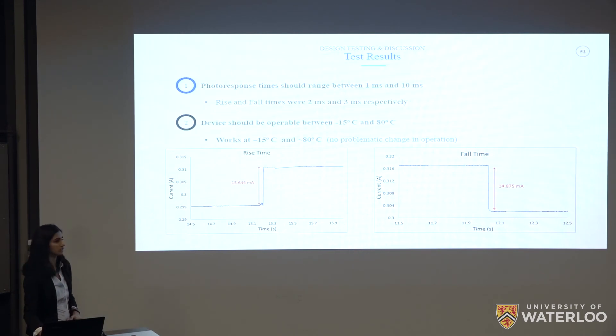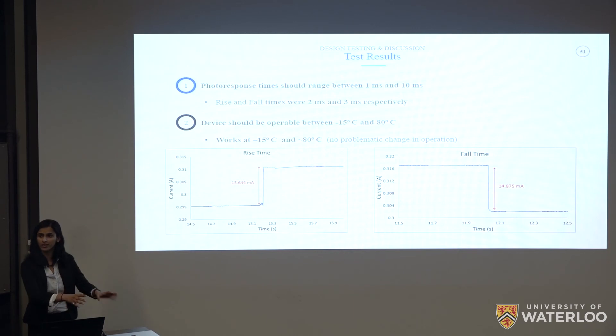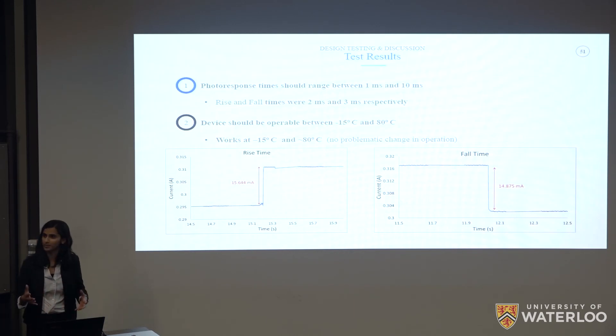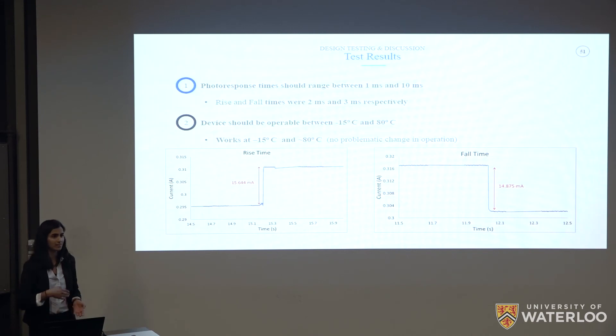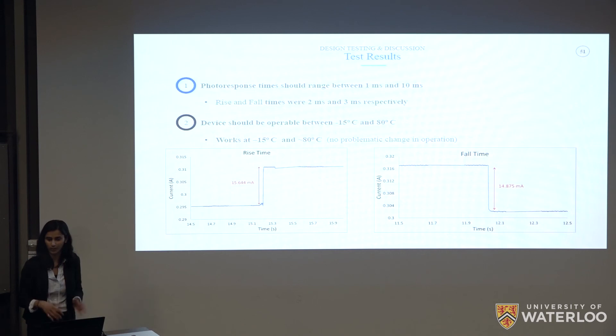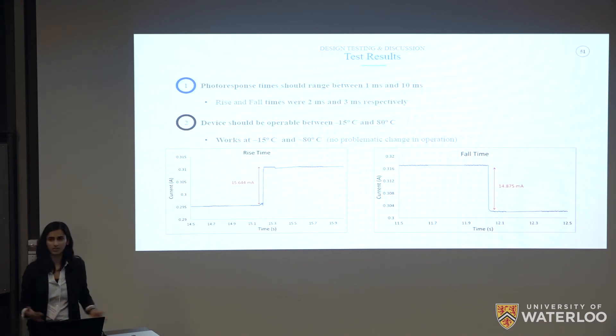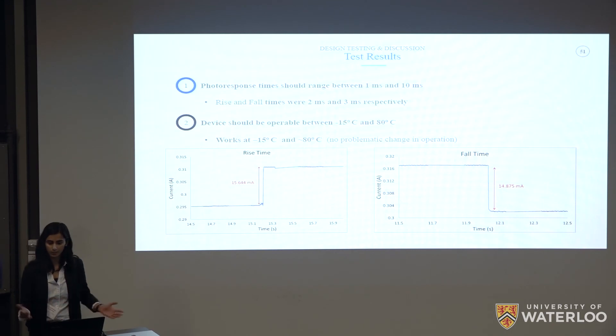We tested the device at negative 15 degrees Celsius by placing it in a freezer and probing immediately after, and at 80 degrees Celsius by heating it on a hot plate and probing as it cooled to that temperature. We observed no significant change in operation, only a slight change in signal-to-noise ratio — nothing too drastic.